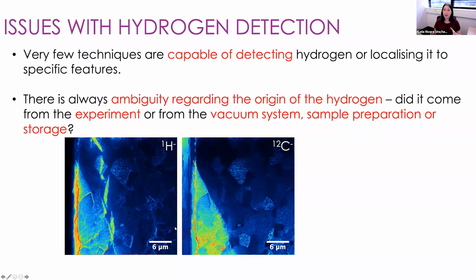Now, when we look at the carbon map that we acquired simultaneously, we can start to understand things a little bit more clearly. So what I didn't say is that over on this side here, this is resin. We mounted this sample in a resin so that we could polish it and hold it in the sample holder. And an image such as this may take half an hour to 1 hour to acquire.